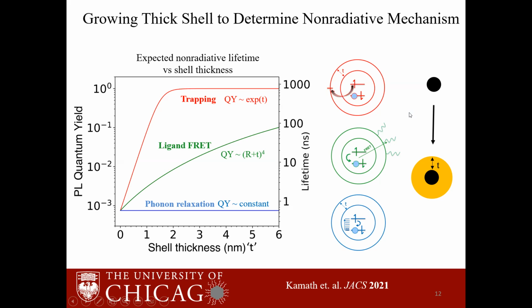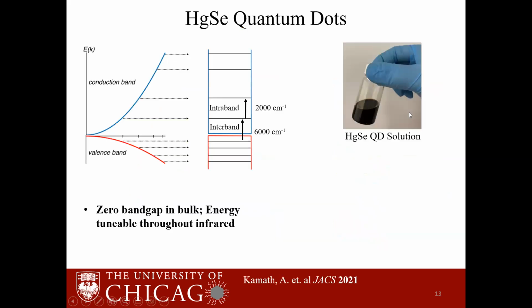So looking at these three trends, we have an elegant method to determine the relaxation mechanism. So what we need to do is grow shells of different thicknesses, compare our experimental trend to these three simulations, and this will tell us what the relaxation mechanism is. Growing a thick shell on quantum dots is not an easy task, and it is especially hard for mid-infrared quantum dots. We have used mercury selenide quantum dots as the material for mid-infrared emission.